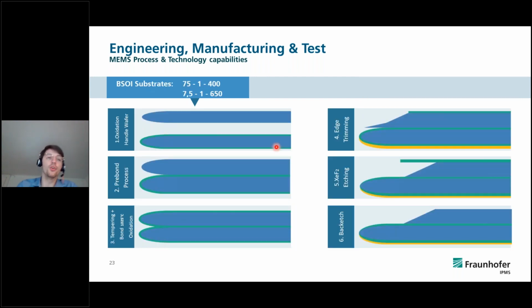So what were the goals? We wanted to bond 2 wafers, and our goal was to do a BSOI substrate in this run with 75 microns, 1 micron of oxide and 400 microns of silicon, and the other one was 7.5 microns, 1 micron of oxide and 650 microns of silicon.